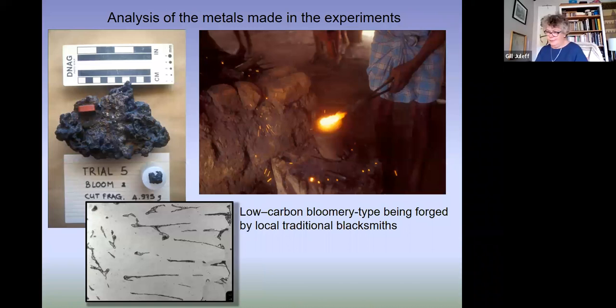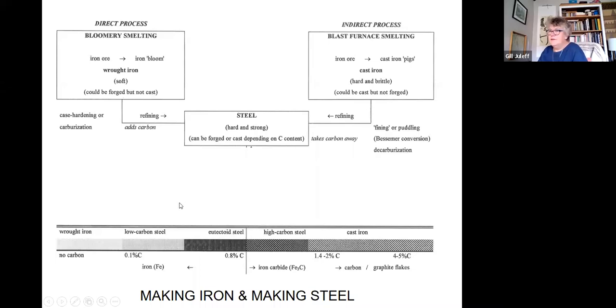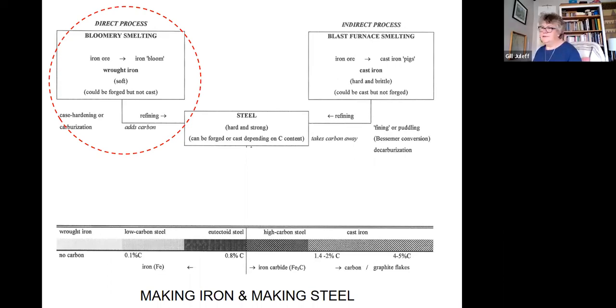So what he had smithed from our bloom was in fact low carbon bloomery iron, just the sort of material that we were seeing in that diagram in the pre-industrial traditional process. And here's a microstructure of that metal, very little carbon in it, and it's relatively soft. It's the sort of stuff that we would find coming from a process at this side of our route to steel, from the bloomery pre-industrial side.